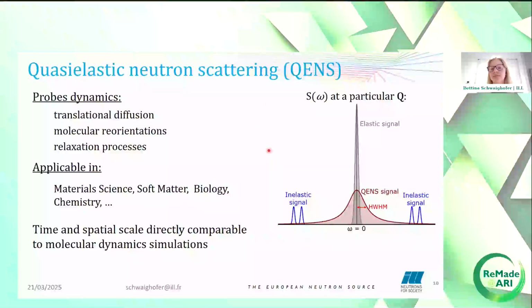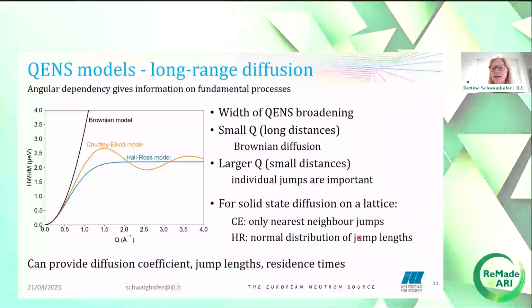Here you can see a schematic diagram of the results you might obtain from a QENS experiment, with the elastic line as a delta function at zero energy transfer, which broadens into a Gaussian due to the finite instrument resolution. Inelastic scattering is at larger energy transfers, and centered at zero is our QENS signal, which shows as a Lorentzian with a certain half-width at half maximum, and this is called the QENS broadening. This broadening of the elastic peak, the Lorentzian, can give us information about fundamental processes.